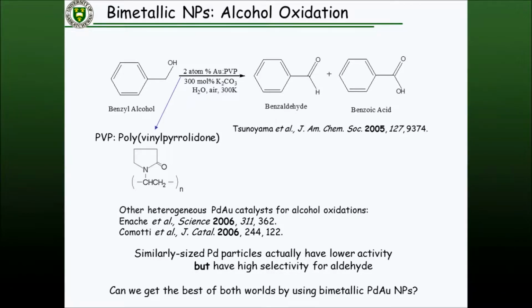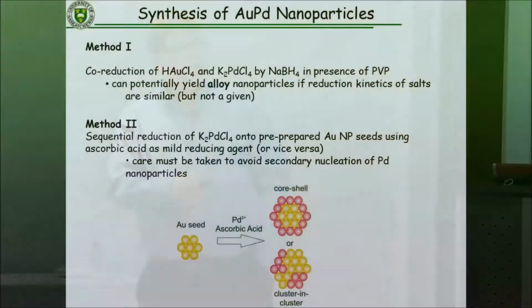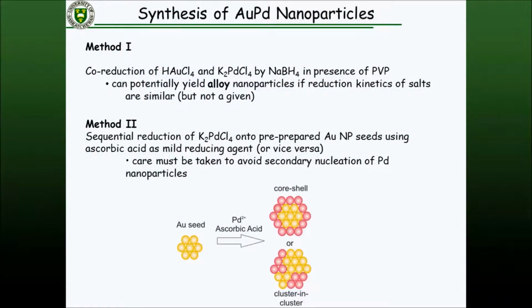We had some previous experience with palladium-gold systems. This is a system in which gold actually had higher activity to the aldehyde and acid than pure palladium did, but palladium systems actually had better selectivity to the aldehyde. So we started playing with bimetallics for this system. We tried a couple of different ways to make bimetallic nanoparticles. The first one is to take both salts and add the reducing agent in the presence of both salts.